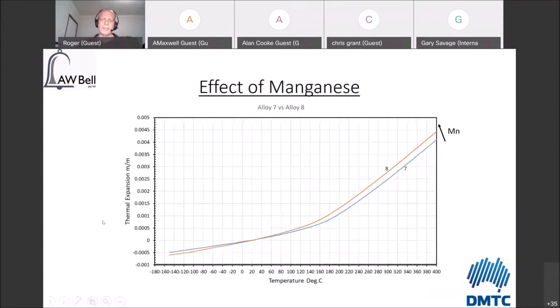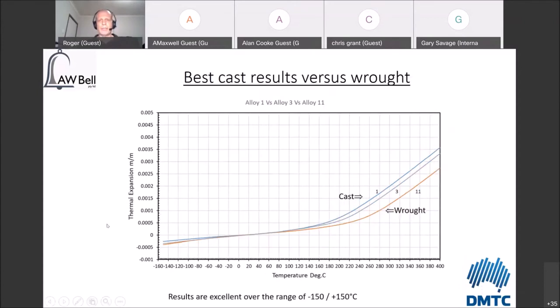Manganese has a similar effect to silicon, although not quite as severe. I've only put two of the curves here, but you can see the general trend is that as manganese is increased, the thermal expansion gets worse. The point of inflection moves to a lower temperature, and it's not the direction you really want to head in, unless you really need to. And when I say unless you really need to, I'll get to reasons why you might add some of these things back in later on.